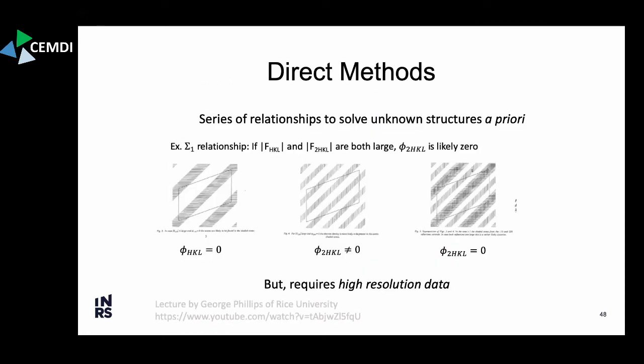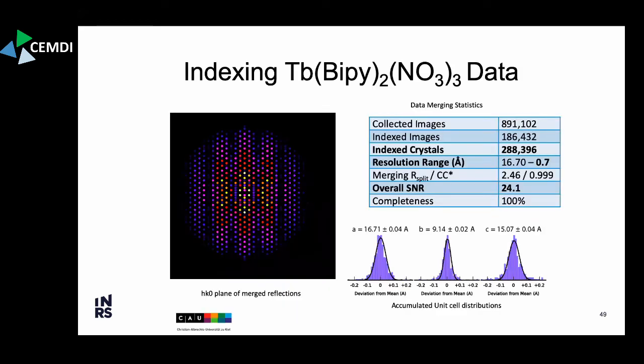But again, this has a problem of obtaining high resolution data. I used this on the data set that I showed you, and I had to index all the way up to 288,000 crystals. And that came from actually 187,000 images in order to get the resolution and the signal to noise ratio to the level to be able to solve this structure. So is it really necessary to go to that level? Necessarily, only if you want to. That's limited by the structure determination algorithm that you use at the end. But there is still a lot of reliable information at lower resolution that was unattainable.